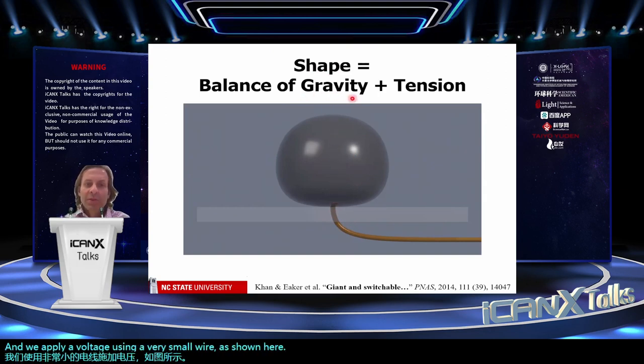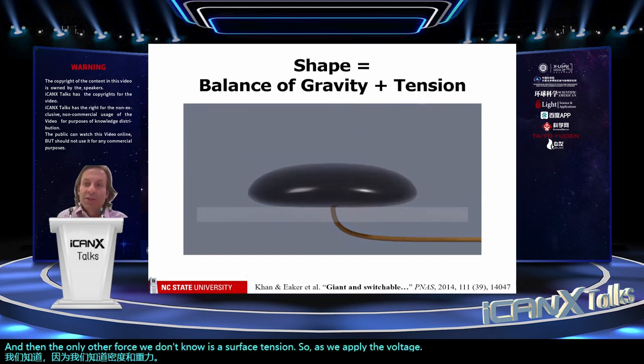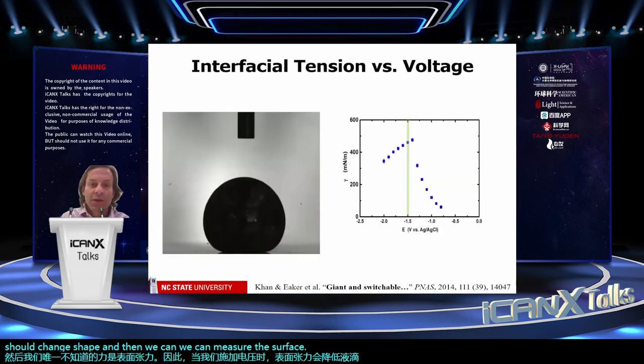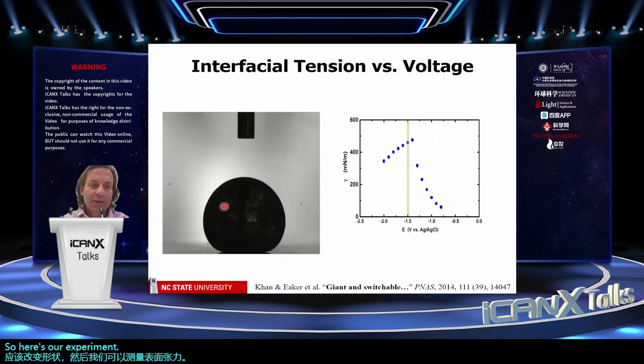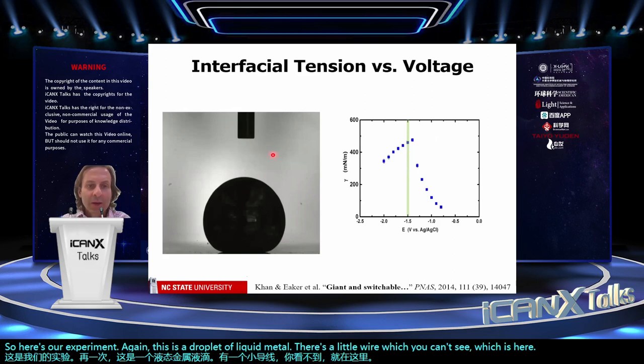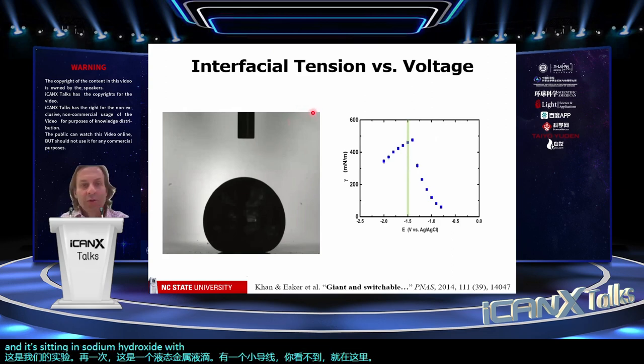And the shape is a balance of gravitational forces, which we know because we know the density and we know gravity. And then the only other force we don't know is a surface tension. So as we apply the voltage, the surface tension gets lower, the droplet should change shape, and then we can measure the surface tension. So here's our experiment. Again, this is a droplet of liquid metal. There's a little wire, which you can't see, which is here. And it's sitting in sodium hydroxide, which is the electrolyte. And there's a counter electrode right here, which you can't see.